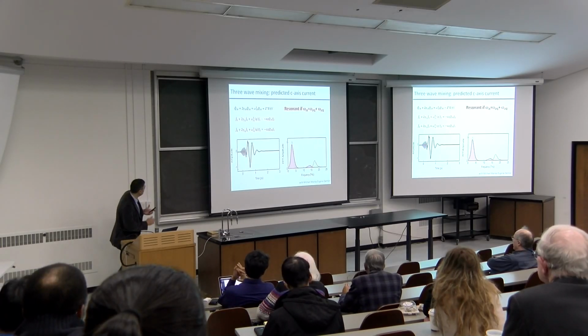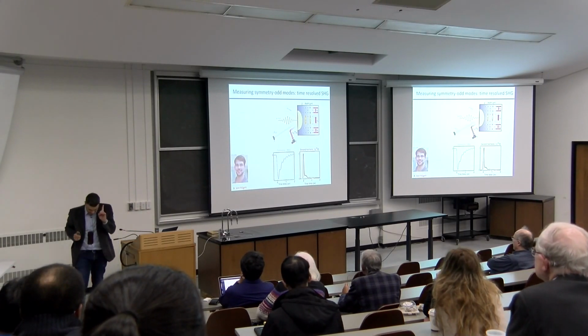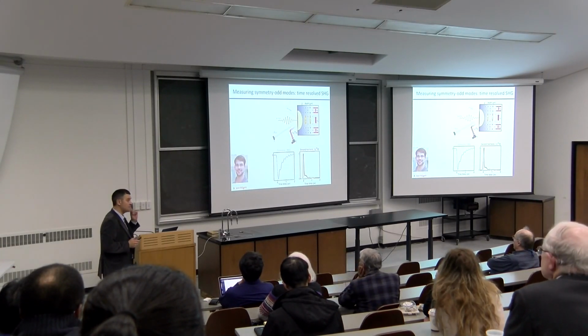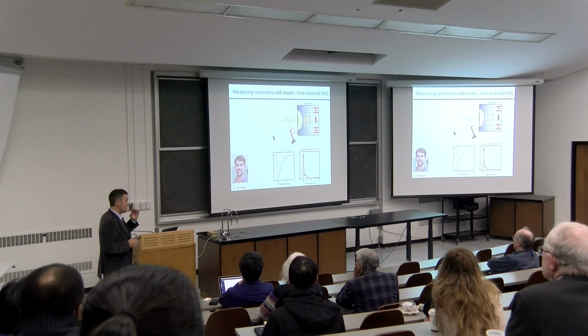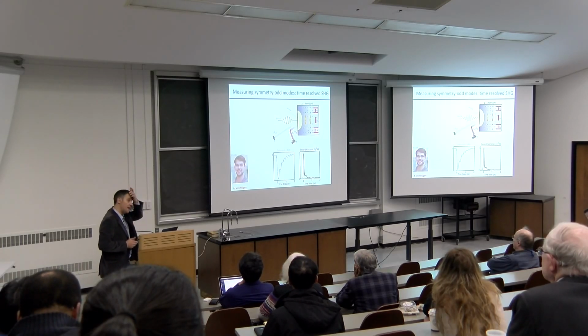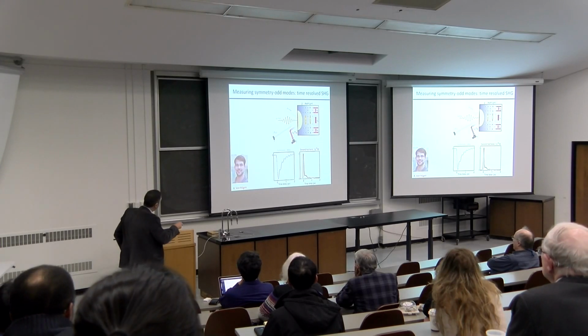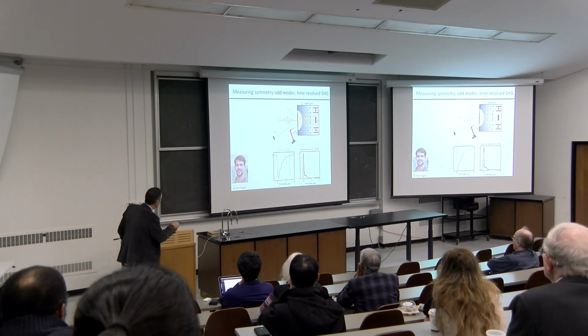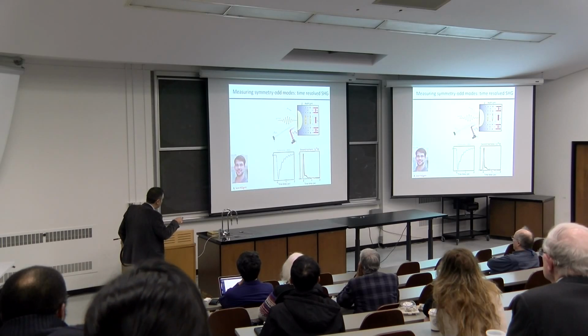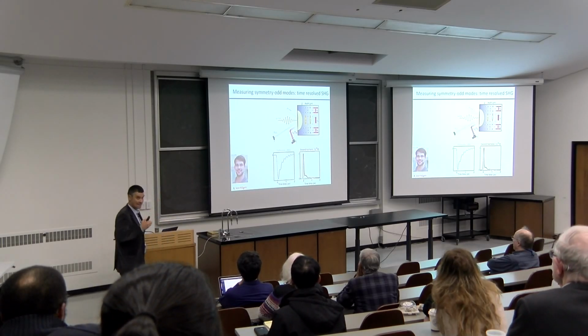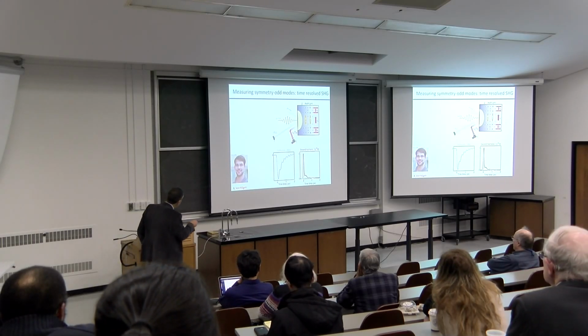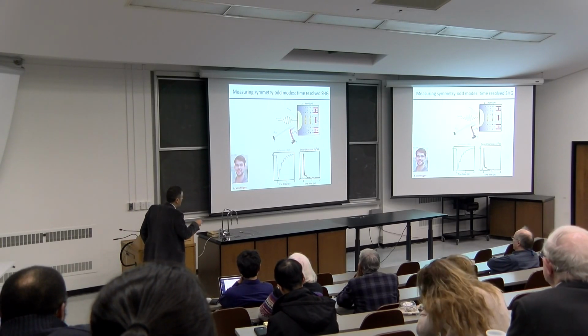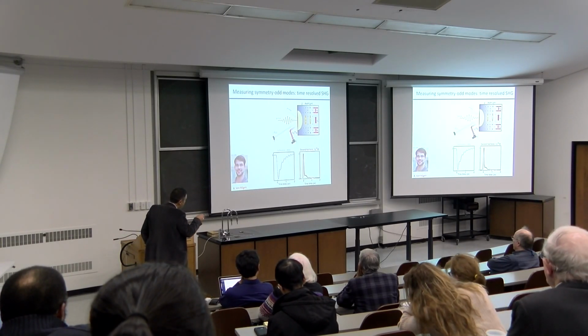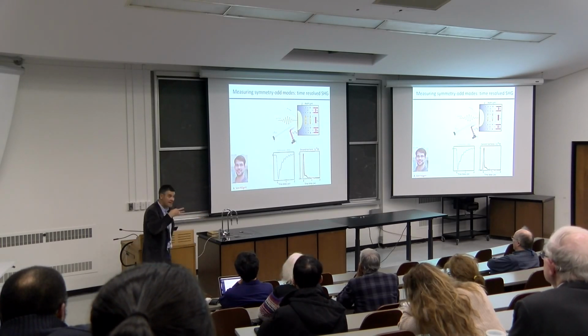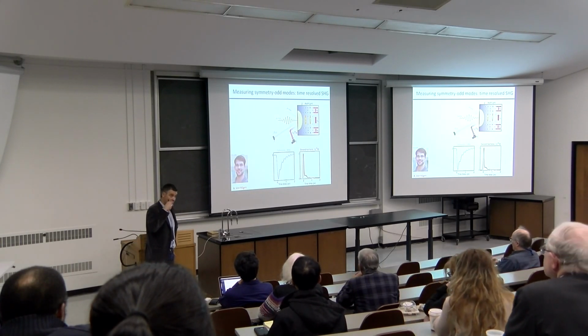Okay, so normally, if you want to measure the coherent responses in a material, people do a pump and then use a probe pulse, say in the visible. They look at the reflection. This is the basics of a pump probe experiment. However, this experiment really only measures totally symmetric modes, whereas if I pump here and I look at the second harmonic of the probe, I'm going to measure the odd modes. This is basically the same experiment that we did for the ferroelectric.